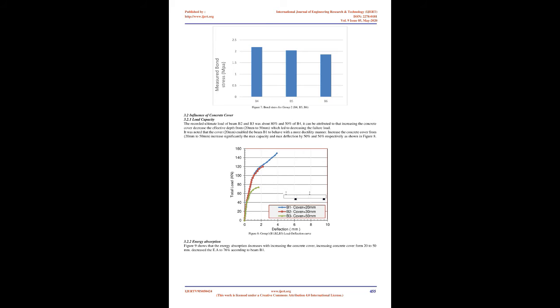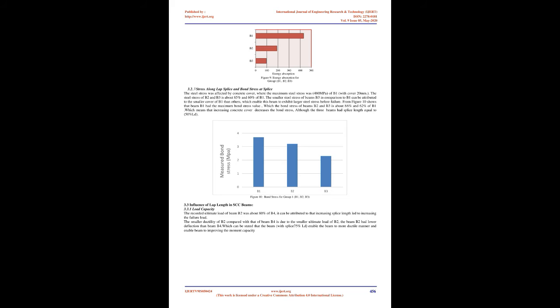From the area under the load deflection curves of both beams B4 and B5 in Figure 5, it was found that this area of B5 is about 78% of B4 and the area of B6 is about 37% of B4, which means that beam B4 has larger ductility. This can be correlated to the influence of higher stirrups intensity within the region of maximum shear strength, not constant shear strength. It was also noted that the contribution of stirrups in improving ductility in beams of normal strength self-compacting concrete is significant because of the large lateral deformation of NSSCC.